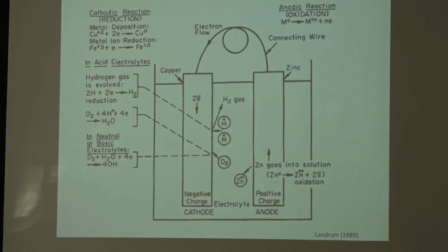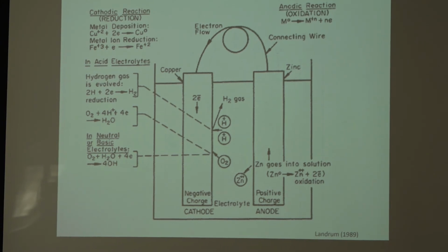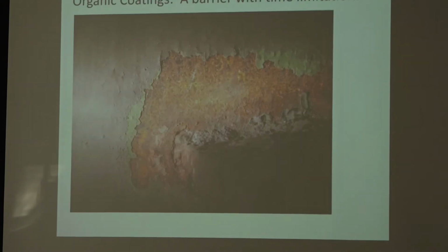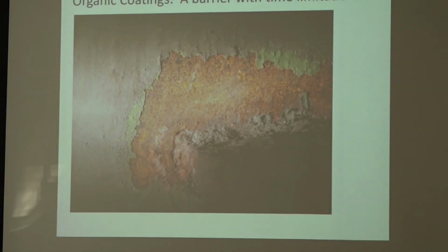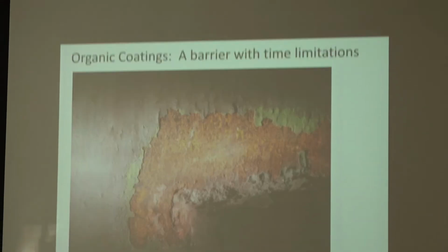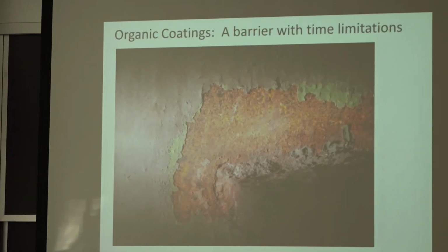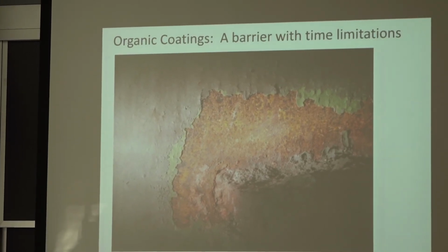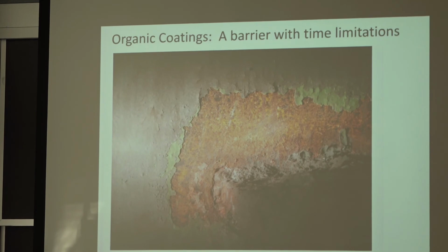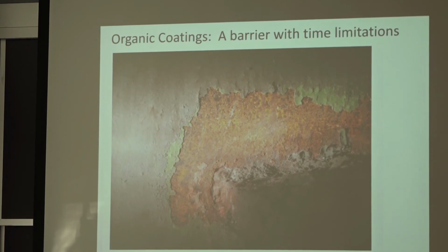Okay, so how are we going to avoid corrosion? We're engineers. We can understand the problems, but we also want solutions, right? So the first thing is it'd be great to put on a paint. I showed the example of the storage drive tunnel where you can see they tried it. They put paint twice. There's an old layer, there's another layer. The issue with paint on steel is you don't only need to protect against the chloride, you need to protect against moisture and oxygen. And that's very hard because it's an organic coating. So over time, it will get through and start the corrosion.